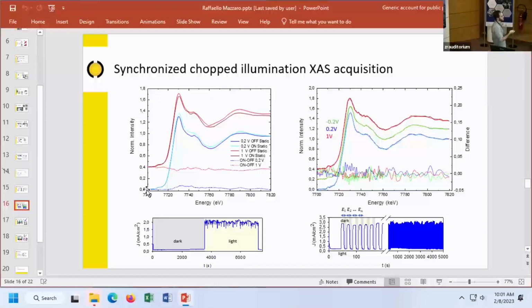So we tried to change the acquisition mode. We implemented a new mode in the beamline that was basically triggering the LED source directly during the acquisition of the excess spectra, so that we could collect energy by energy both the off and on signals, so the dark and light conditions, in order to have information about the fluorescence intensity and therefore the absorption coefficient at each energy, and then switch to the next energy to collect the whole spectrum.